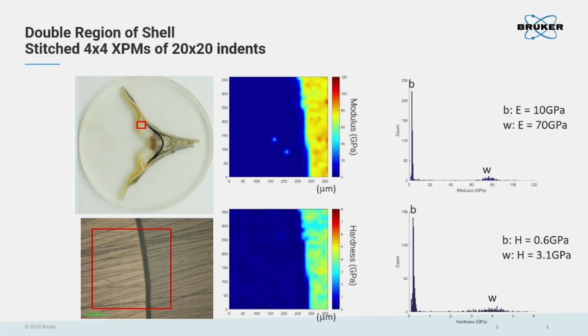So we use nano indentation to make an indentation array to characterize the hardness and modulus distributions, just like Jimmy mentioned. One single indent can provide us one hardness and one modulus. So if we perform a lot of indentation tests over this chosen area, then we have a lot of modulus and hardness values with their corresponding coordinates. Then we can have this color map to get an idea of the modulus distribution together with the hardness distribution. Typically we use a warm color to represent a high value, and on the other hand a cold color to represent a lower value.